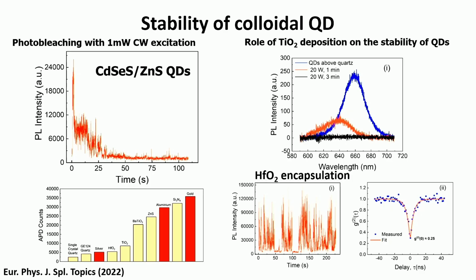So we showed that, by studying a wide range of these materials, dielectrics and metals, hafnium dioxide and gold is the optimum condition for which we could suppress the blinking and also prolong the lifetime of the nanoparticle emission up to 25 seconds. We could show that it's working, and we showed single photon emission from these structures with the patch antenna on the top.